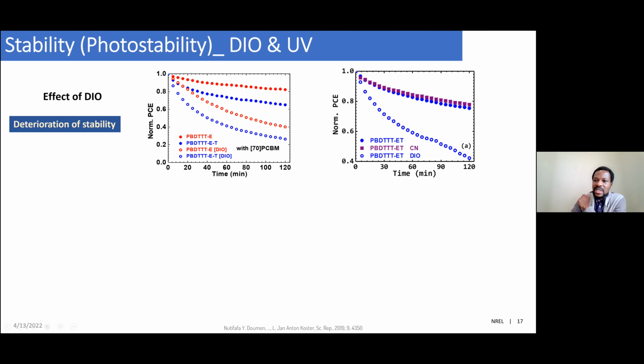And here clearly you can see that when you use chloronaphthalene, you are able to retain your device stability as it was without the additives. And also, of course, the efficiency is similar or slightly improved. So there should be something peculiar about DIO which reacts with the light.